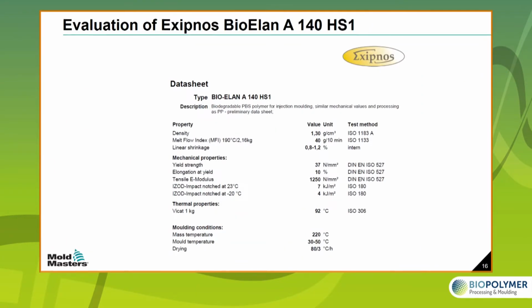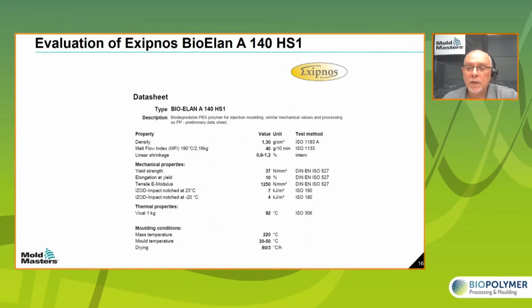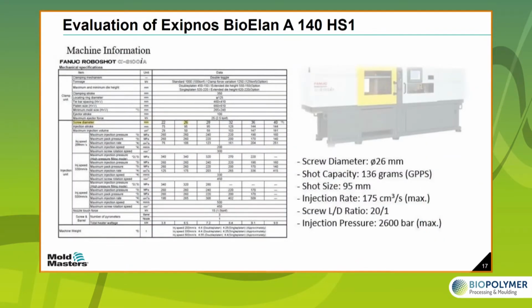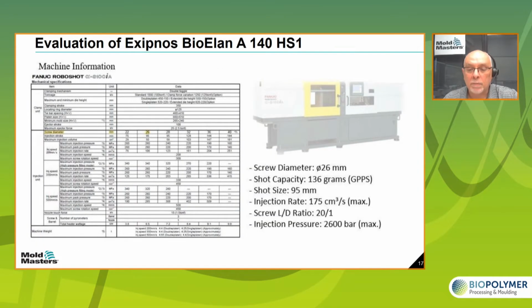So we did an evaluation of a material supplied by BioElan A140HS1. This material is a biodegradable PBS polymer. So it is a biosourced material and it is fully biodegradable. We evaluated it in our test facility using our injection molding machine, which is a RoboShot, just a regular machine, a general purpose screw diameter 26 millimeters, capable of 2,600 bar. We're nowhere near that with these materials in this closure mold.